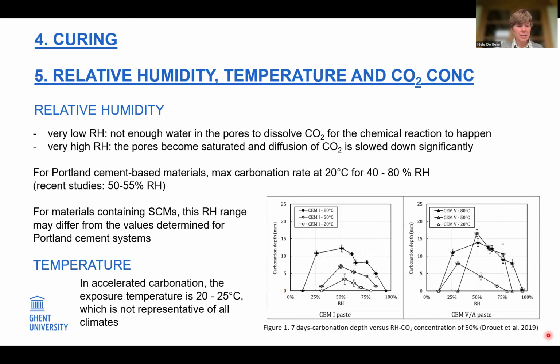Some other important factors like curing is of course very important to limit carbonation. We also know that carbonation is proceeding the fastest at intermediate relative humidity levels, but it's not very clear if the range is the same for concrete with SCMs as for ordinary Portland cement concrete. And then temperatures, higher temperatures generally accelerate carbonation as the chemical reactions and diffusion will occur faster.